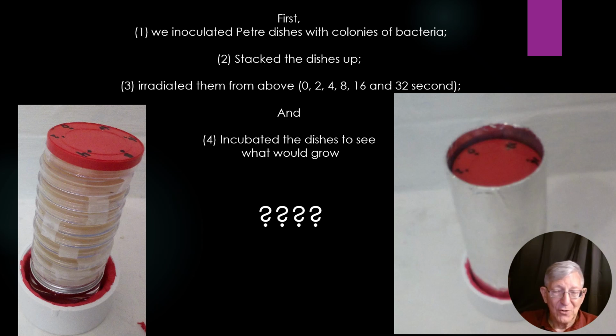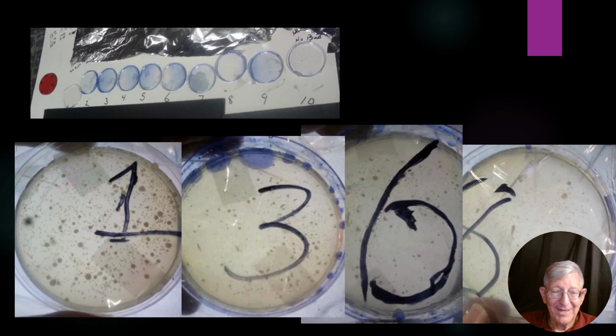Within 18 hours of inoculation, we took the whole system over and exposed it to proton beams for the allotted amount of time. We took the samples back home, disassembled this whole thing, and let it essentially incubate for a couple of days. And then we took a look at what we had. Number one was the top item, which received the least linear energy transfer. And you'll notice that there's a pretty healthy growth of different bacteria over here.